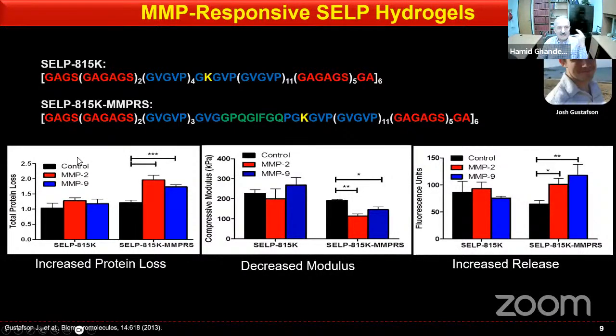So what you see on the lower hand side, so we spent some time, we made one prototype and later a couple of other prototypes where we could precisely control the location of these MMP responsive sequences in the polymer backbone. What you're seeing on the lower hand side, let's say, is the total protein loss, which is protein that is resulting from the degradation of these protein-based polymers. On the left-hand side, this is SELP815K. This is the parent polymer that doesn't have the MMP responsive sequence. You see a certain amount of protein loss, but when we incorporate the MMP responsive sequence, in the presence of two different types of enzymes, MMPs, you see an increase in release of the protein, which is basically increased degradation of the material.